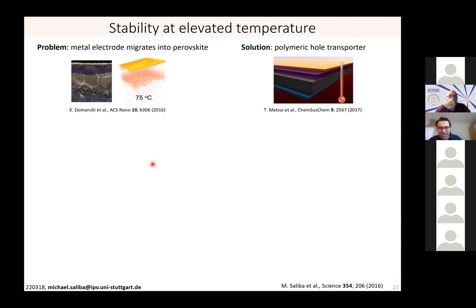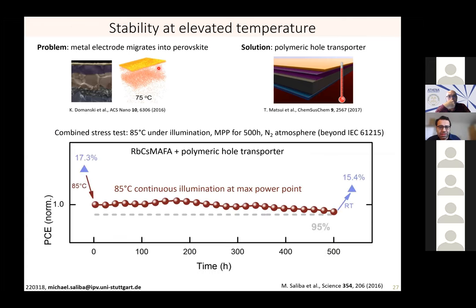Then, of course, the very important topic of stability. So here, maybe two quick results. First of all, we found that the metal electrode seeps into the perovskite layer, degrading it through the organic HTM, a hole transporter material. And one solution which we found in a smaller study was that a polymeric hole transporter could be a good way to prevent this.